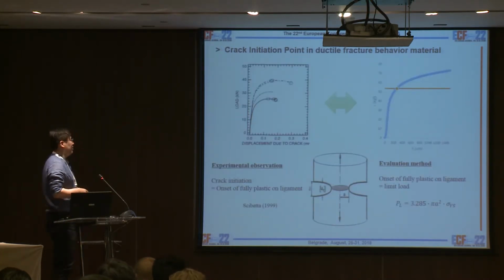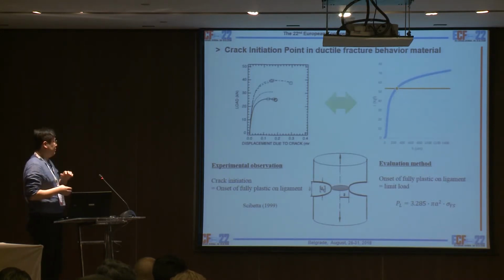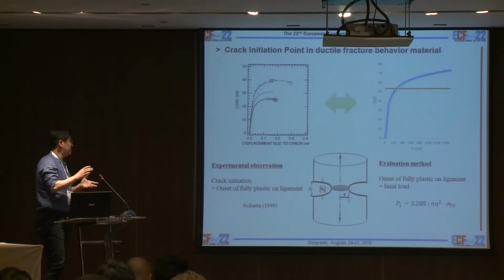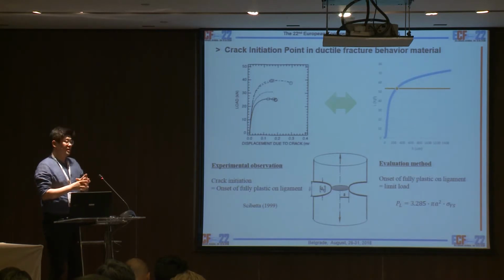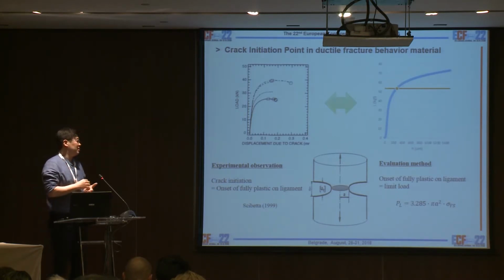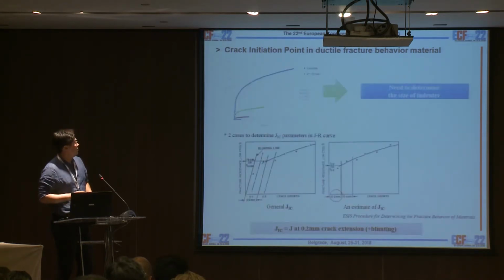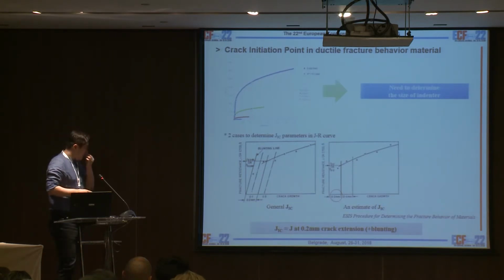So experimentally, the crack initiation point in a cracked round bar is the onset of fully plastic behavior on the ligament, and that point is calculated by the limit load, so we can determine the limit load point in normalization curves. But still we need to determine the size of the indenter. So in this case, we adapted the experimental point of view.